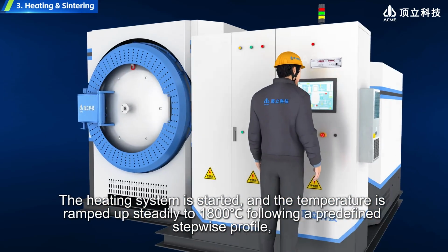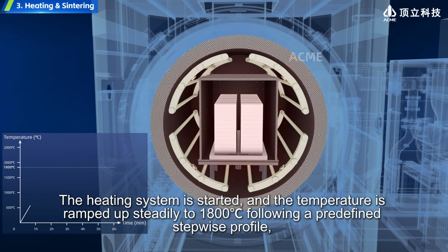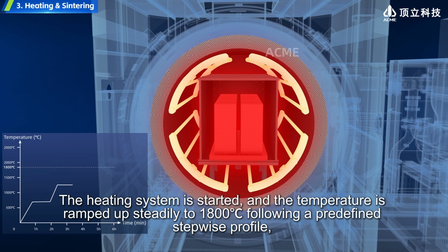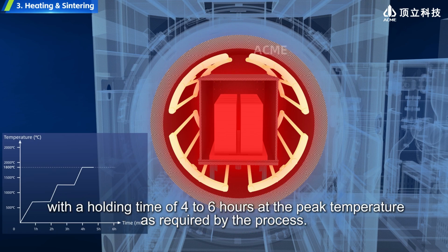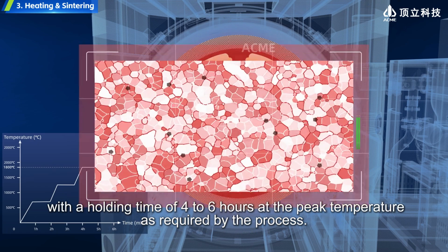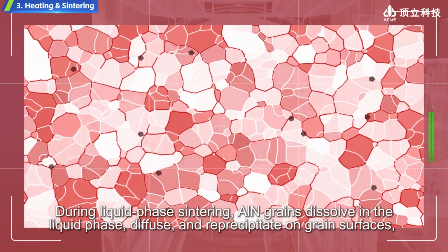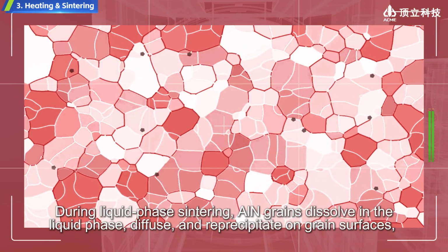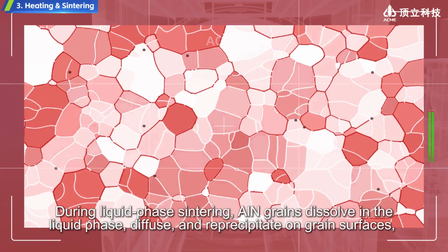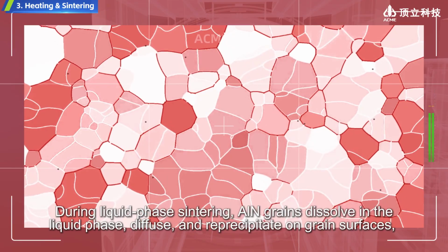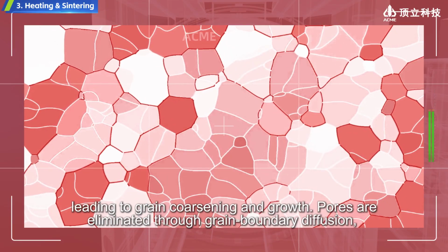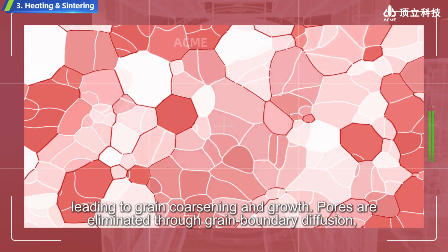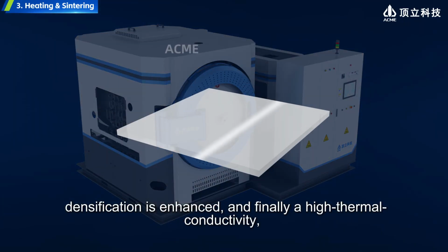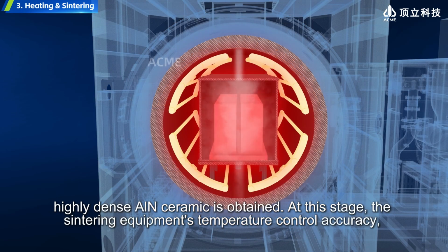pressure. The heating system is started, and the temperature is ramped up steadily to 1800 degrees Celsius following a predefined stepwise profile, with a holding time of 4 to 6 hours at the peak temperature as required by the process. During liquid phase sintering, AlN grains dissolve in the liquid phase, diffuse, and reprecipitate on grain surfaces, leading to grain coarsening and growth. Pores are eliminated through grain boundary diffusion, densification is enhanced, and finally a high thermal conductivity, highly dense AlN ceramic is obtained.